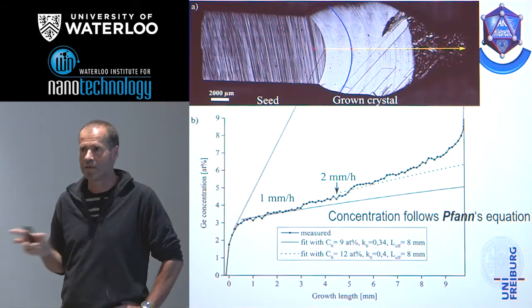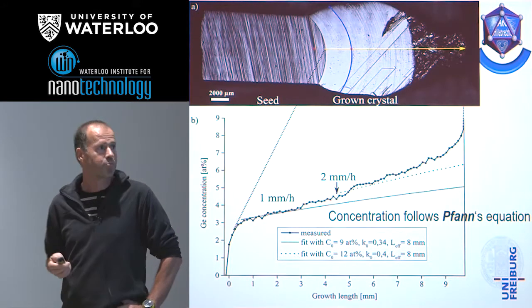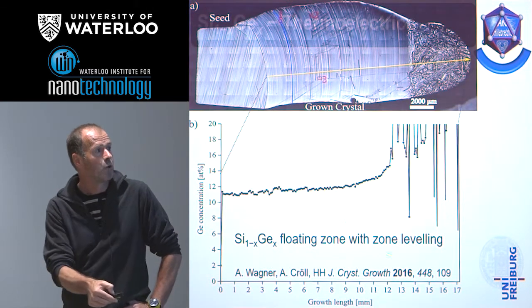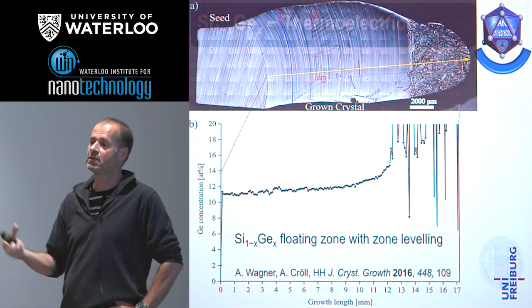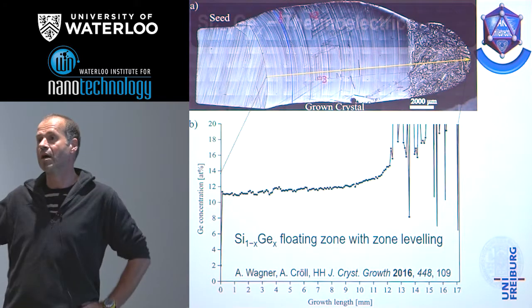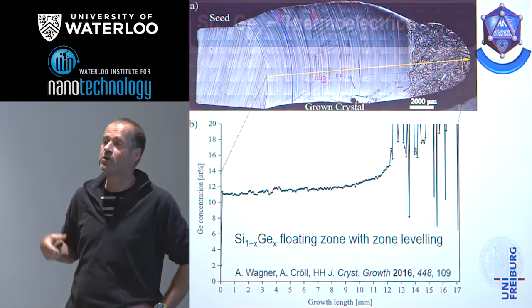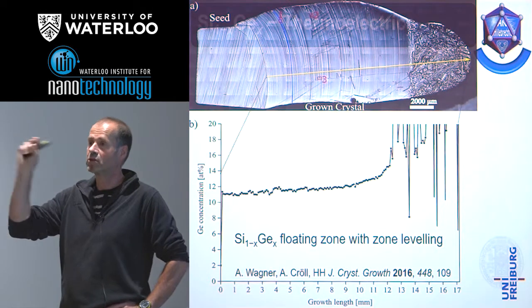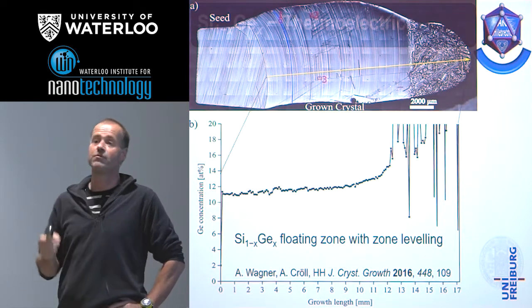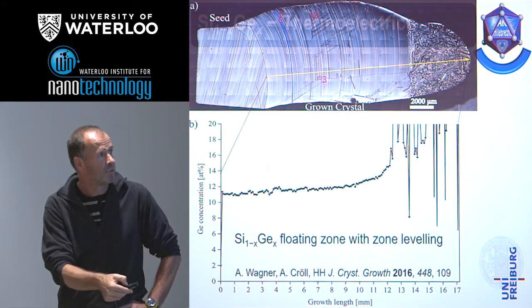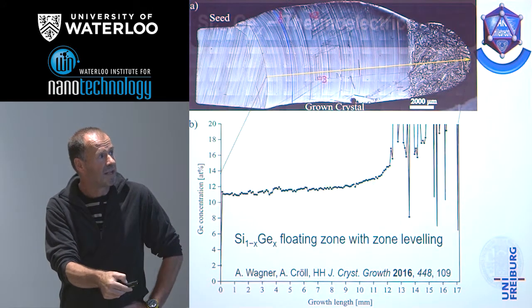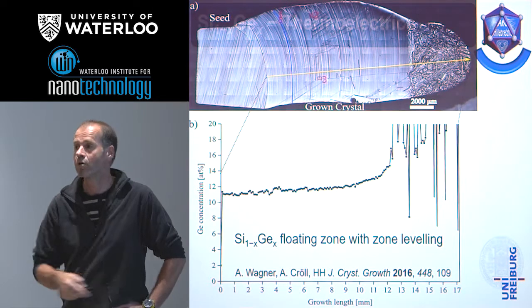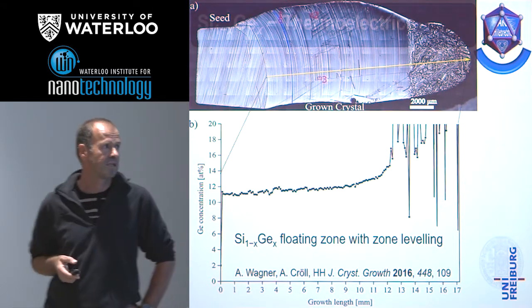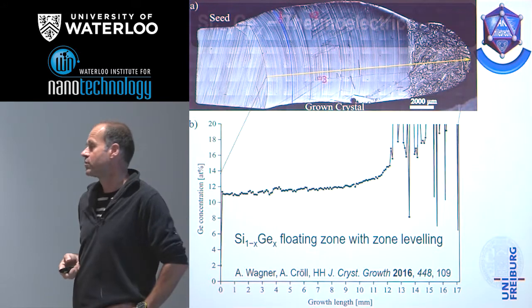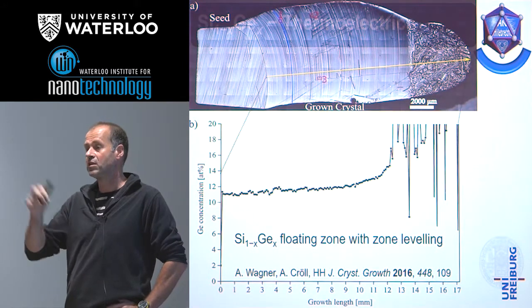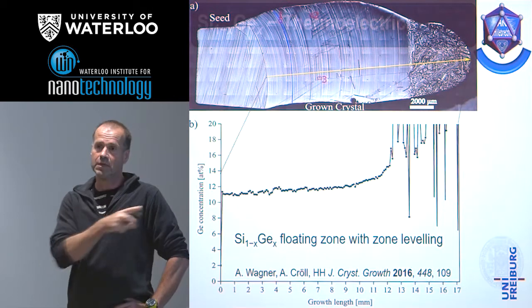And when we could show that it works indeed with this Pfann's equation to get well-developed single crystals without further twinnings and others, we changed the process according to a zone leveling. That means we could estimate with which additional amount of germanium we should start. We could synthesize a pellet with the appropriate content of germanium, and starting with this modified feed rod, we were able to grow single crystals with a well-defined and nearly homogeneous content of germanium. It's one of the very first examples that we could grow single crystals of homogeneous solid solutions of silicon and germanium in that way.